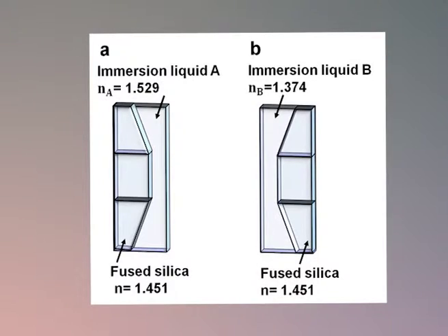The difference in the refractive index is indicated by the amount of contrast between the glass and the immersion liquid. The fragment is then removed, washed and placed in another liquid with a refractive index closer to the match point. This is repeated until the refractive index of the match point has been deduced, that is, by using a succession of liquids with different refractive indices, the refractive index of the sample can be deduced.